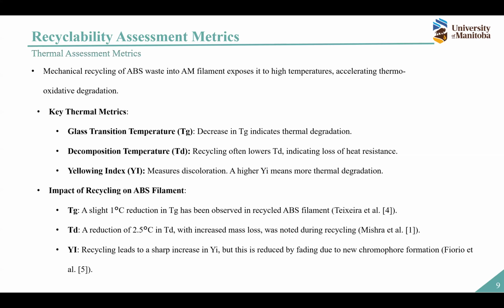So also the thermal assessment metrics. The mechanical recycling of ABS waste into filament exposes the material to high temperature, which exposes it to thermal oxidation degradation. So to measure this degradation mechanism, we need to do experiments to measure a specific type of metrics, the thermal assessment metrics. The most important thermal assessment metrics are glass transition temperature, decomposition temperature, and the yellowing index. For example, you can see that Mishra and also Fiorio tried to measure these thermal metrics to investigate the effect of recycling on the material properties.